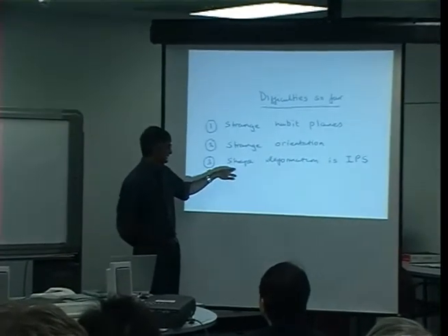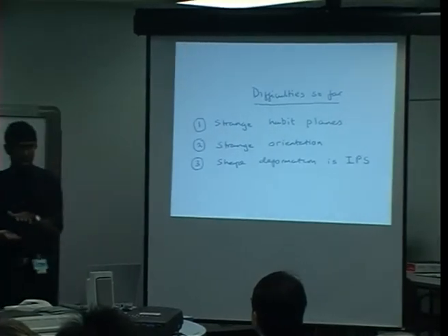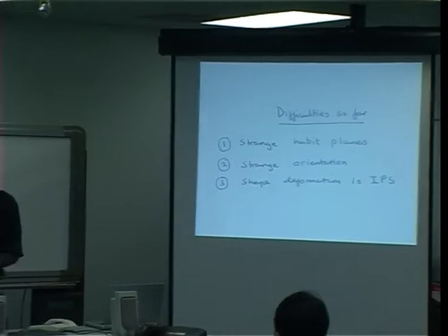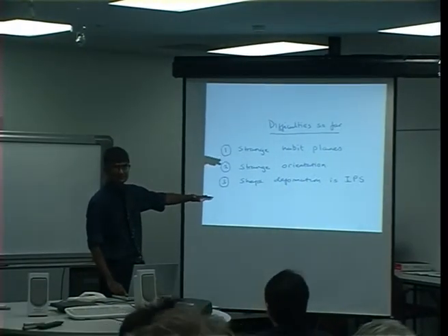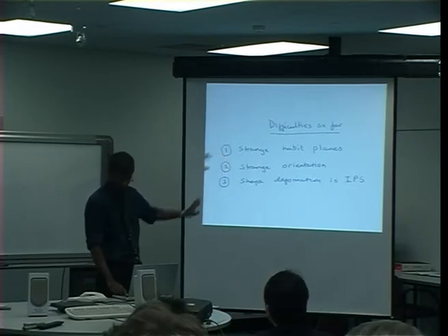And I explained that the shape deformation we observe indicates that there is a coherent interface between the parent and product. And I'm now going to demonstrate that it is actually impossible to get a coherent interface between austenite and ferrite. So even this last statement is inconsistent with the crystallography. So everything is confusing at this stage.